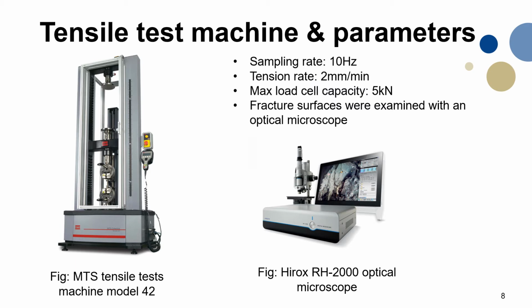And this is the tensile test machine and the parameters we have used for this research. We have used the MTS tensile test machine model 42. It has a maximum capacity of a 5 kilonewton load cell. For the sampling rate, we have selected 10 Hertz, which means we are collecting 10 data points per second. The tension rate is 2 millimeters per minute. And for the fracture surface, we used an optical microscope to examine it.